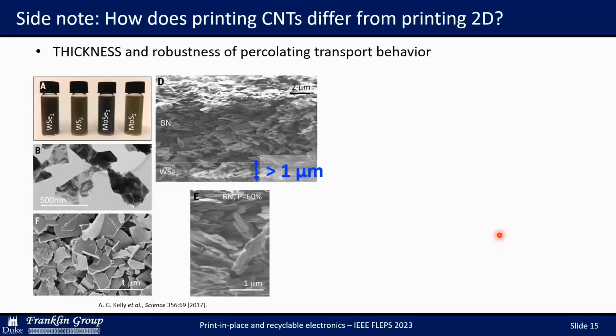So one of the other advantages to printing nanotubes, I want to compare to printing two-dimensional semiconductors, because we're still riding a bit of a heavy buzz wave on 2D materials, which makes people want to do anything they can with them. And so, of course, we've printed them. And I hate to break it to those who haven't done this yet, but they are fairly terrible printed semiconductors. Maybe we'll get them to be better, but part of the reason they're terrible is that they do not print into thin films. They print into very thick films on the order of hundreds of nanometers or microns thick, which does not exactly bear fruits from their two-dimensional nature.